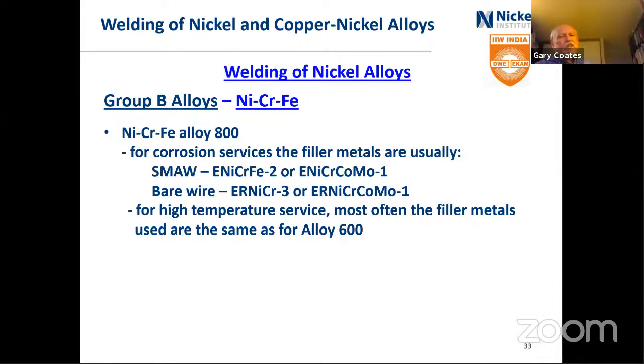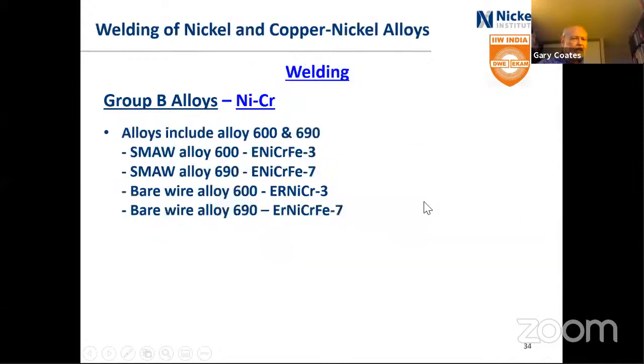Their high temperature service is sometimes very tricky because it depends on how it's used in the high temperature. There's different variations of the grade 800H, 800HT, but most often the filler metals used are the same as for alloy 600, which is the next slide here. The 600 is the shielded metal arc is nickel chrome iron 3, and the bare wire is ER nickel chrome 3. And they are high nickel filler metals.